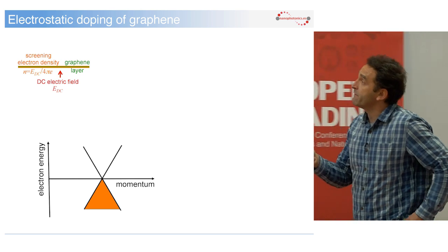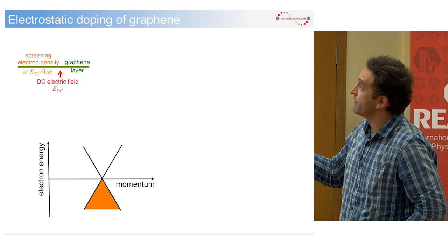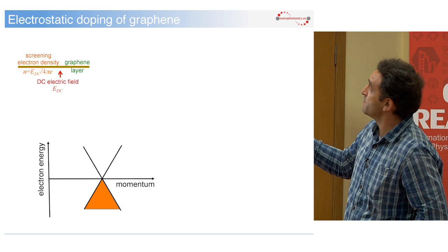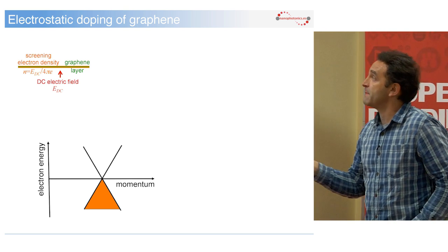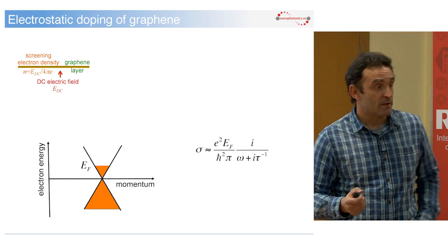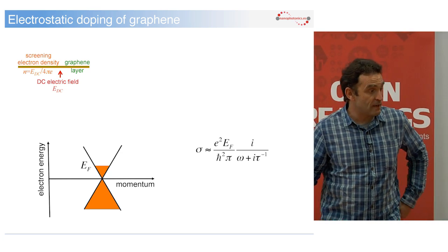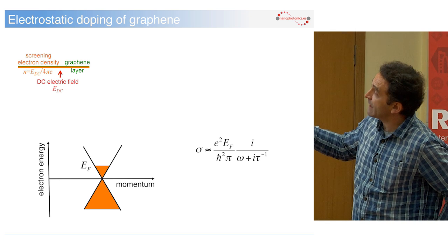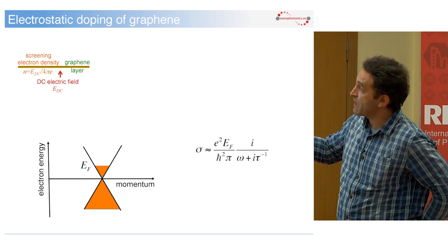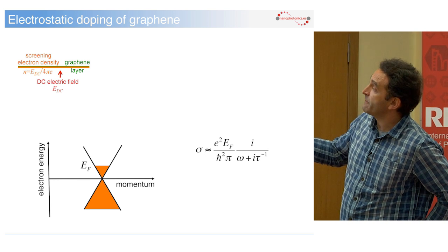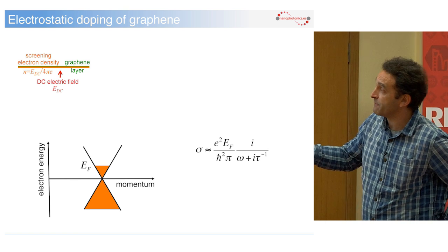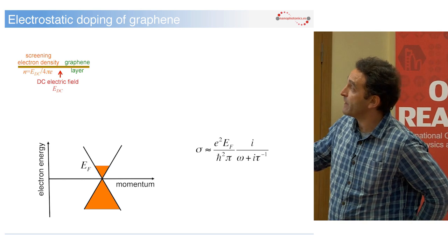So here we have a graphene layer, and then we apply an electric field, which is the electric field coming from the bottom gate in this case, so in this capacitor. And then what I put here is the band structure of graphene. So graphene near the Fermi level has dispersion electronic bands that are like this. They cross the Fermi level at a single point, and the lower band is fully occupied in pristine graphene, and the upper band is fully unoccupied, right?